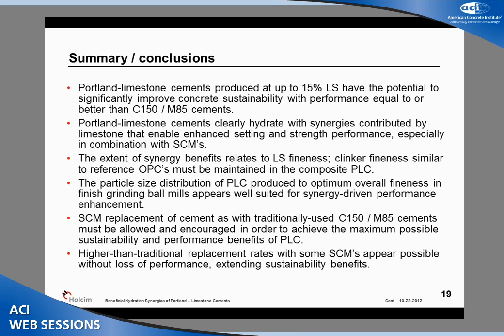One of the things I'd point out that's kind of a stumbling block for us in the industry as we're trying to do the education and promote this material, particularly with DOTs, is that because of the specification category for Portland limestone cements under the new blended cement spec, many DOTs will consider that when you add a fly ash or slag cement, or certainly silica fume, anything else like that, to this system, you now have what they refer to as a ternary system, because the limestone is considered part of the cementitious components as a blended cement. And ternary systems may not be allowed in their specifications. So now we have a caveat to work through.